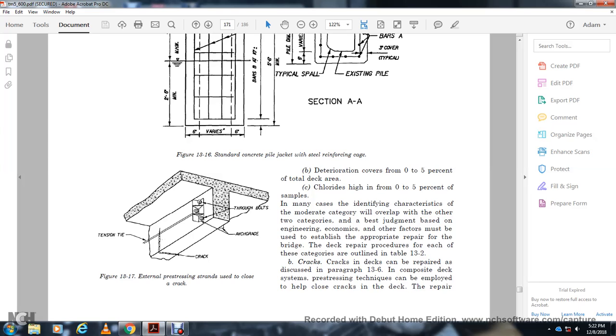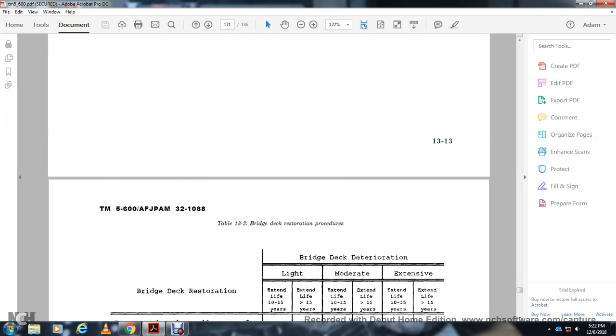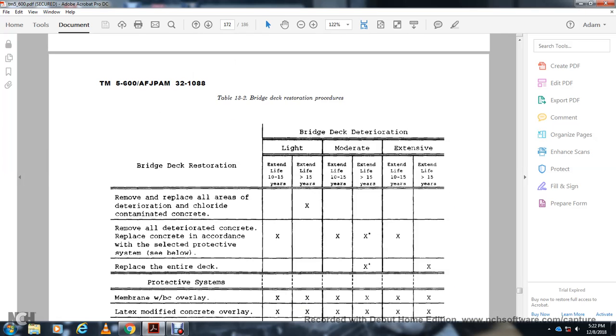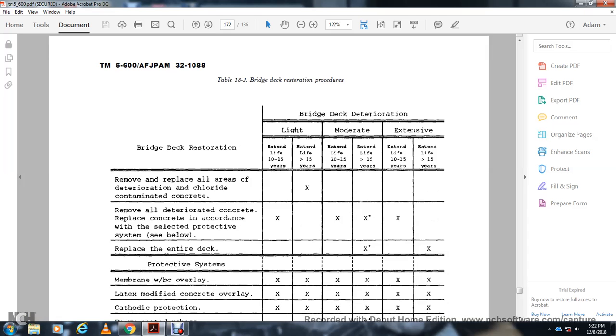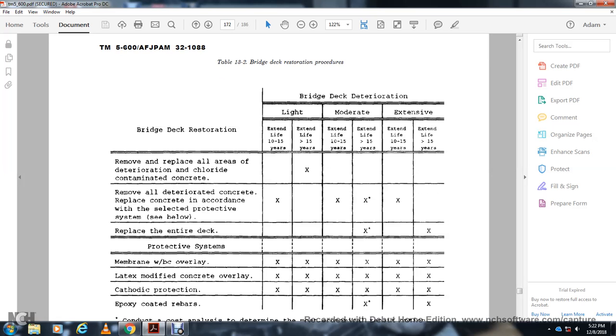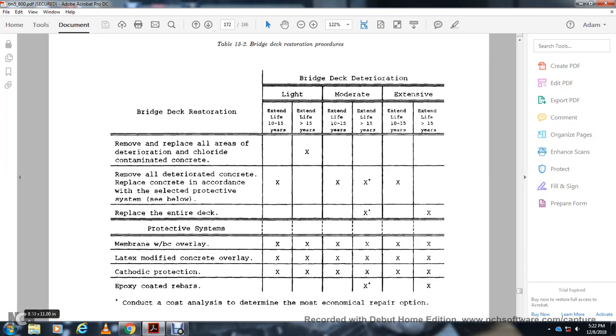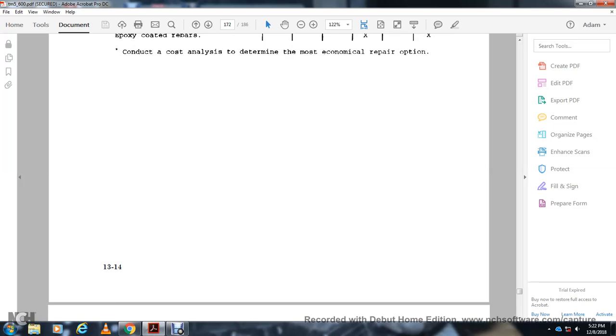The pre-stressing techniques can be employed to help close the crack from the deck repair. And then we show the bridge deck restoration: light, moderate, and extensive. The removal will replace all of the deteriorated, chloride-contaminated concrete. Removal of all the deteriorated concrete, replace with concrete in accordance with the selected protective system. Replace with the entire deck protective system: membrane with an asphalt overlay, latex modified concrete overlay, cathodic protection, epoxy coated rebars.